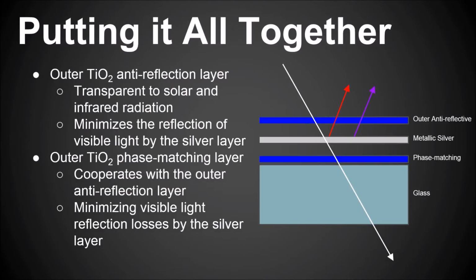So putting it all together, we first use a silver layer of about 50 angstroms thick. This is the best thickness for use in window films. It's not too thick to compromise solar transmission, but it's not too thin to feasibly deposit as a film. Next, we use the two titanium oxide layers that go on the outside. The anti-reflection layer is transparent to solar and infrared radiation, and in conjunction with the phase matching layer, cooperates to minimize visible light reflection losses by the silver layer.